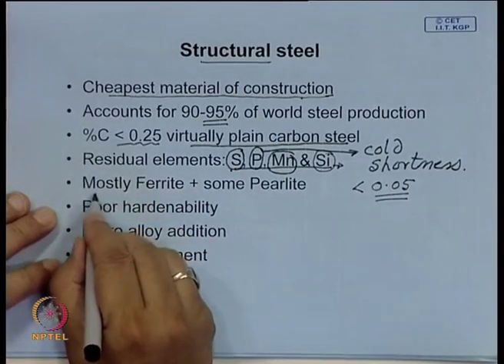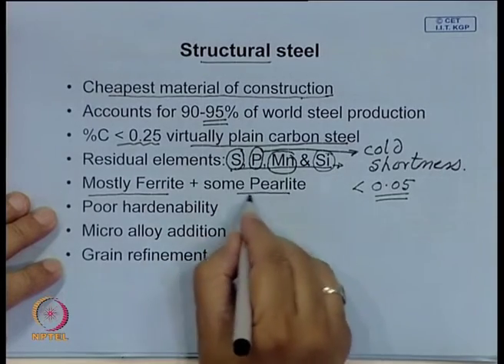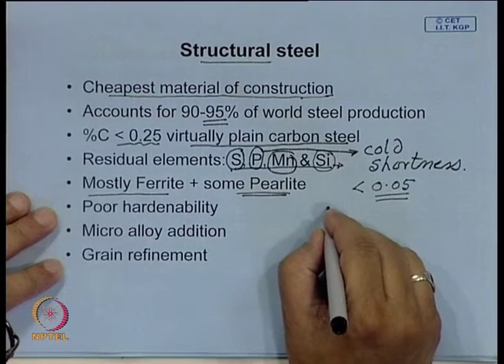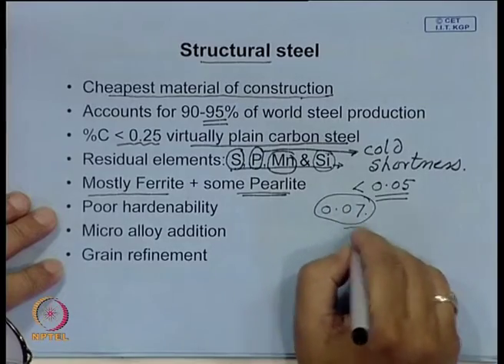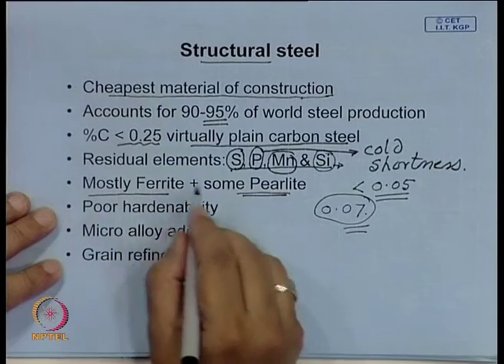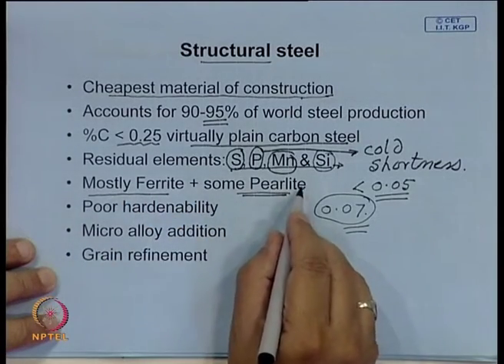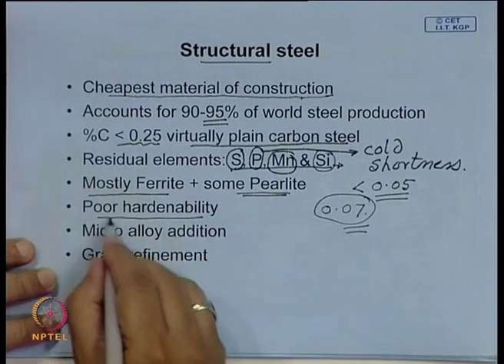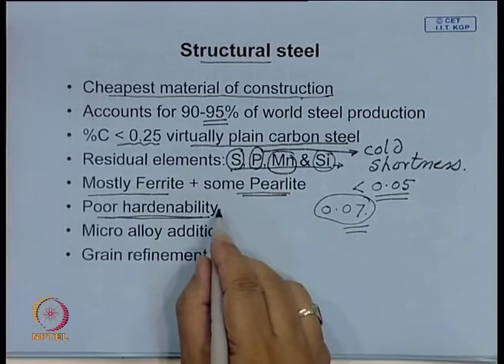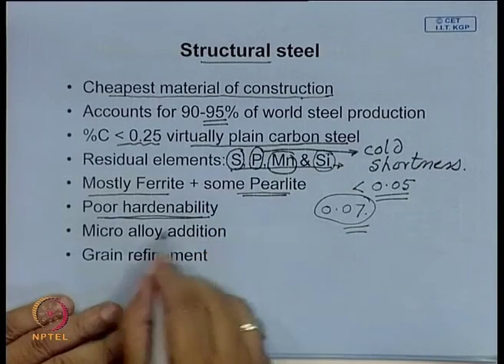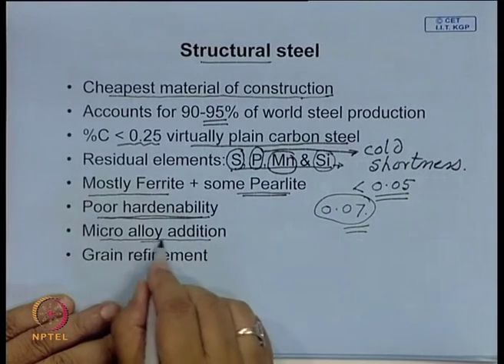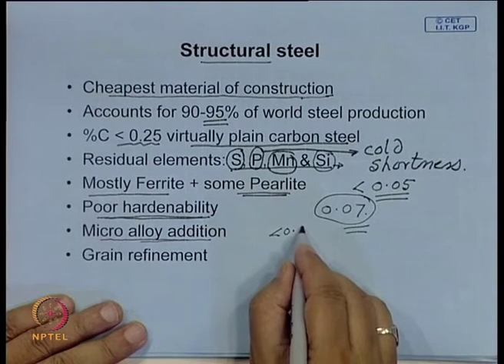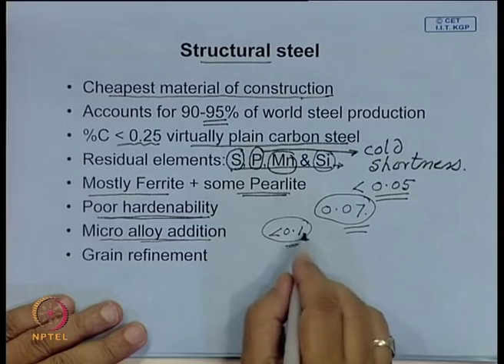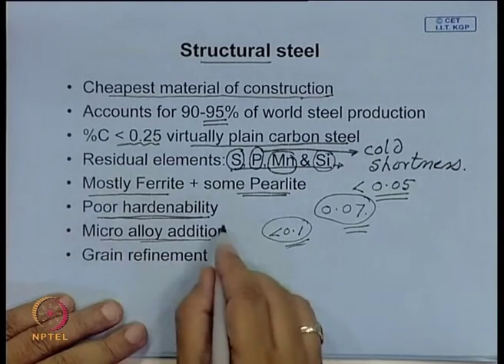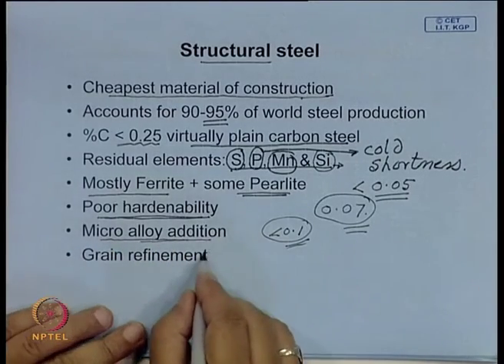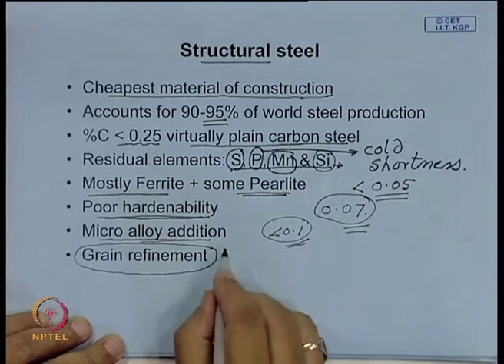And the microstructure of structural steel is mostly ferritic. It may have some pearlite depending on the carbon content. Many of these grades have as low a carbon content as 0.07. So virtually it will be made up of a mostly ferritic matrix, and a very little amount of pearlite. Because it has low alloy element, it has poor hardenability. So martensitic strengthening will not be applicable, strengthening by hardening cannot be done over here. And often you may have some microalloy additions, in very small amounts, even less than say 0.1 or 0.05, and certain elements, if added in such small amounts and combined with thermomechanical processing, make it possible to refine the structure, make the grain size very fine and thus improve the strength of steel.